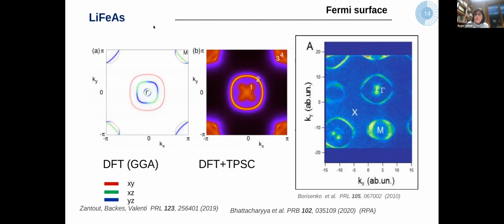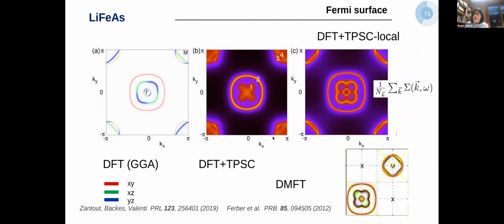So we applied that to lithium iron arsenide, and here I'm showing the results of the band structure and the Fermi surface by DFT. When one applies this combination of DFT with the two-particle self-consistent method to obtain the effect of the self-energy, one obtains a shrinking of these inner hole pockets, very similar to what is observed experimentally. And moreover, very interestingly, if we now do the momentum average of these results, we obtain the result of DMFT. So in fact, even though these are two different approaches to obtain self-energies, one can obtain the other by averaging over the momentum.